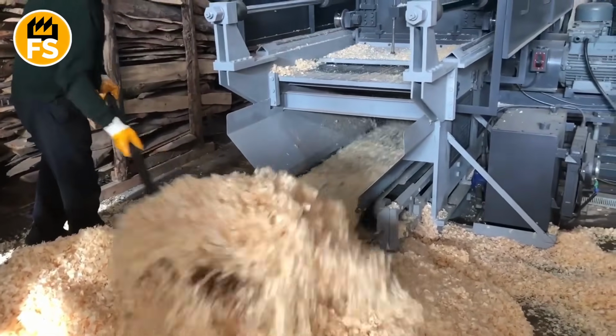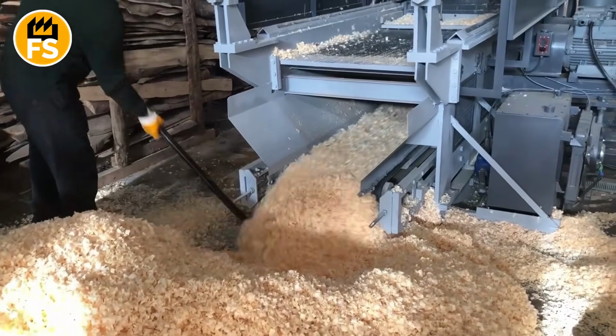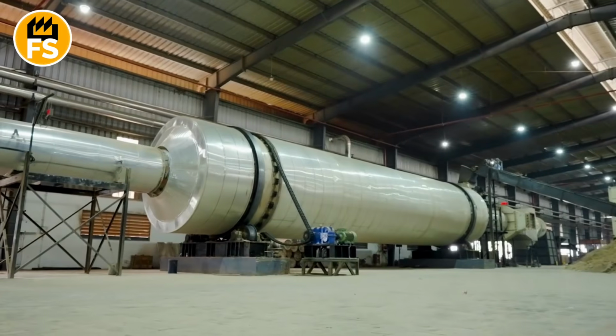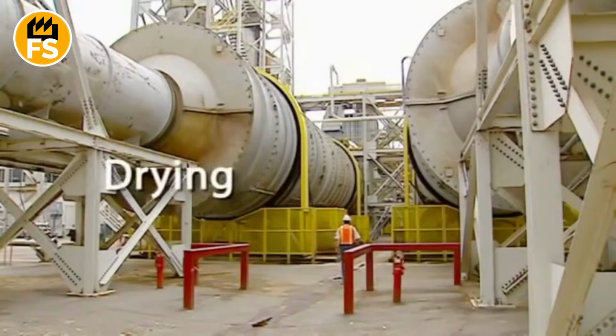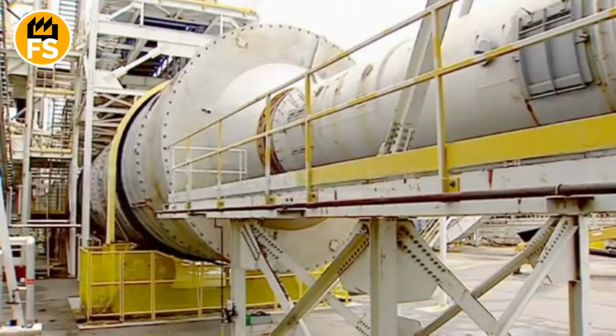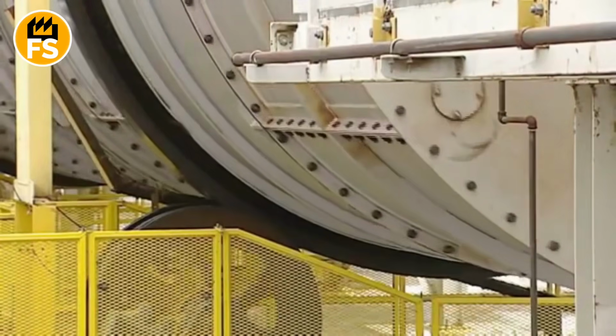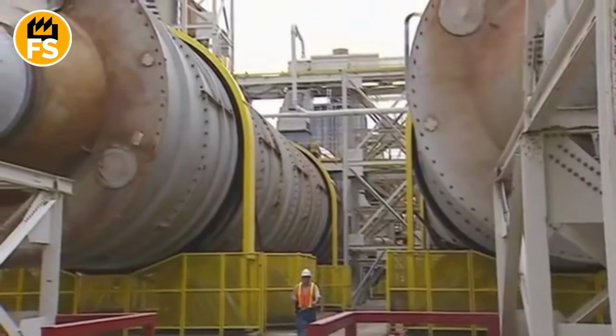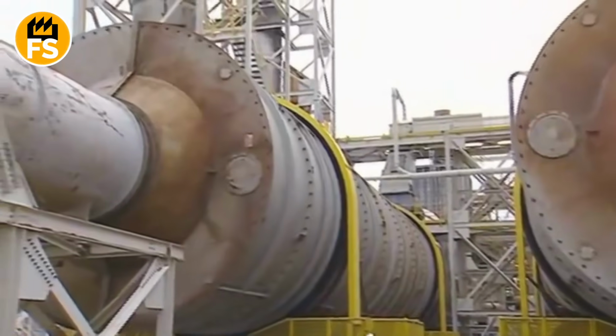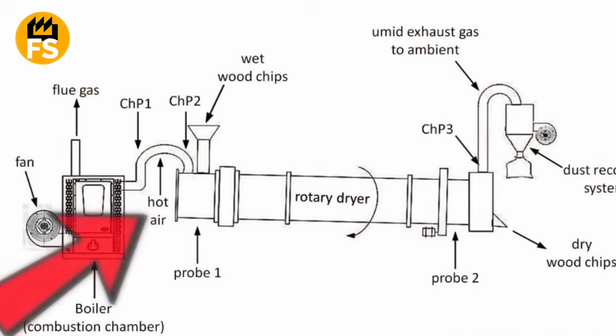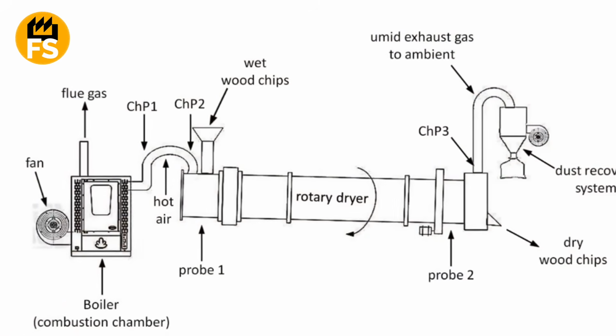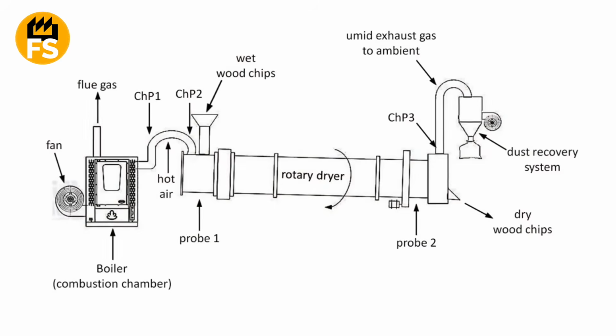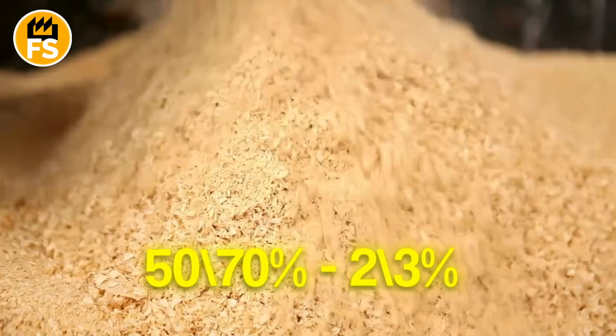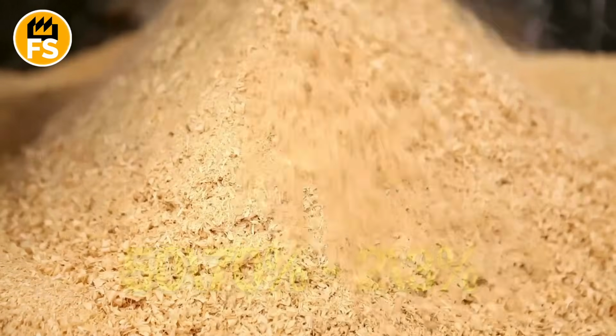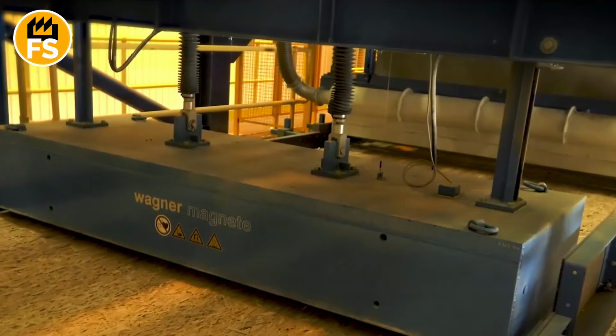The resulting mass of wet, fresh chips, resembling a huge pile of light noodles, is stored in special bunkers, and from there, it is sent for drying. This is a huge, multi-story drum, slowly rotating, half a football field long. Inside it, a high temperature is maintained, and while the strands are slowly tumbling, moving from one end to the other, a stream of hot air evaporates the excess moisture from them. The moisture needs to be reduced from 50 or 70% to only 2 or 3%. This is absolutely necessary so that the resin can properly soak the wood and glue it firmly.